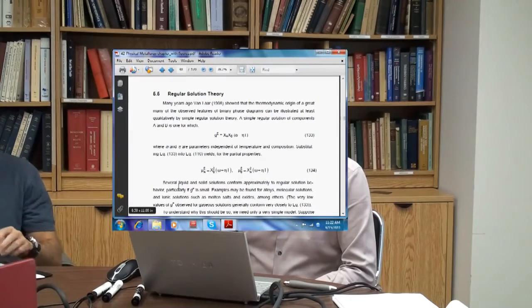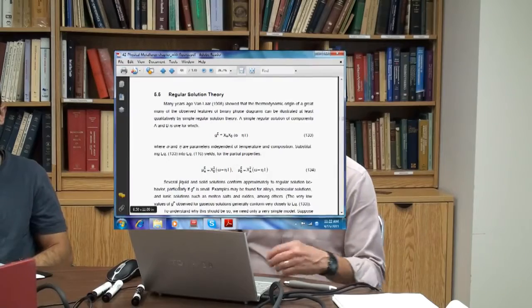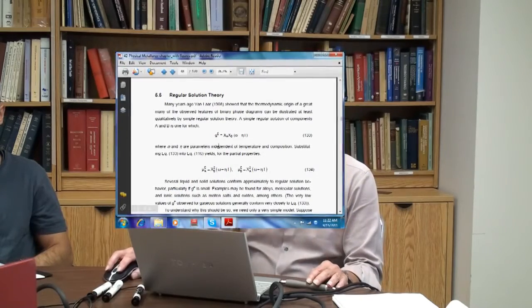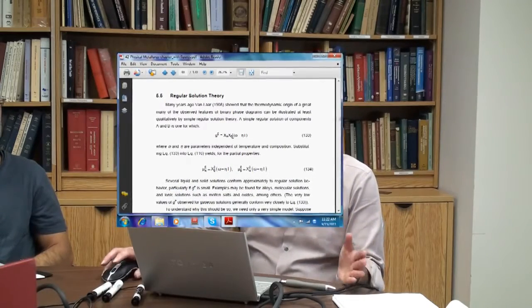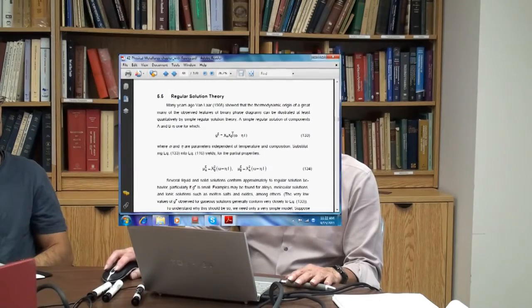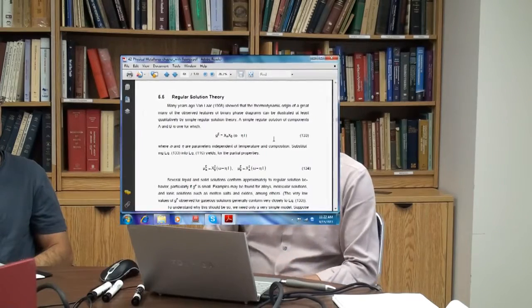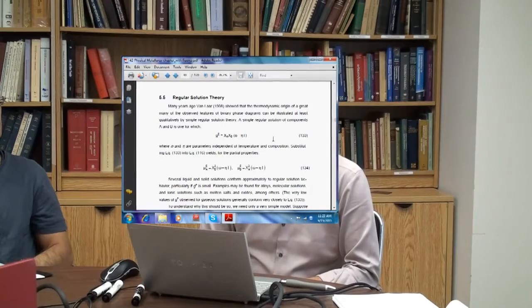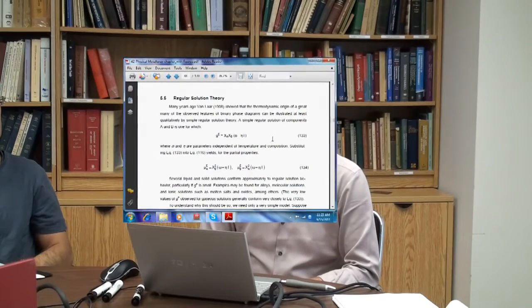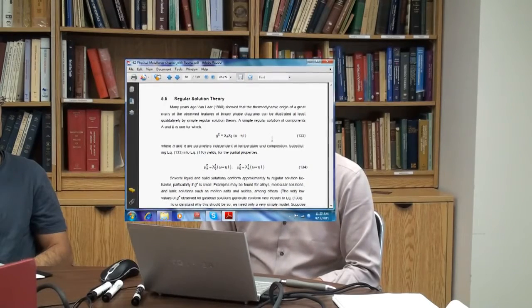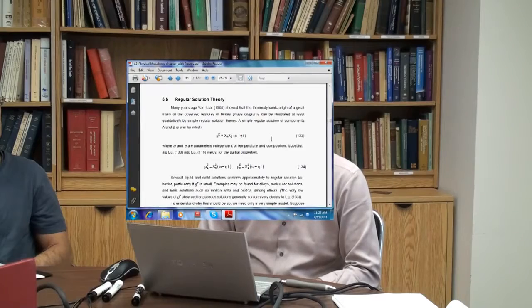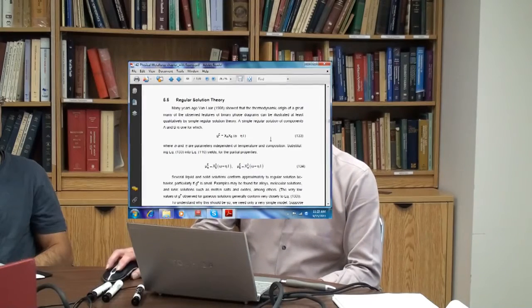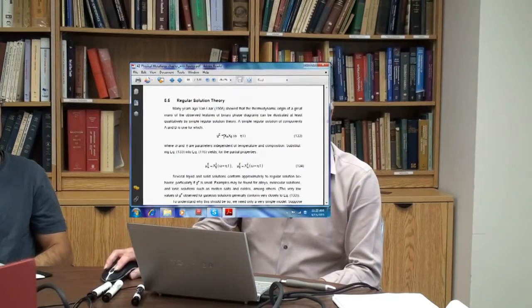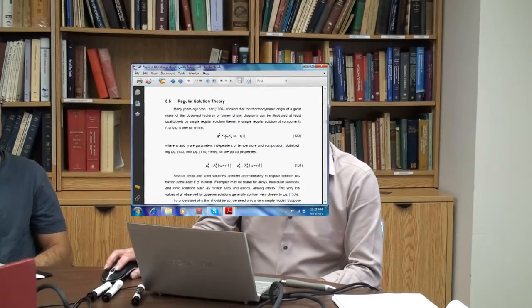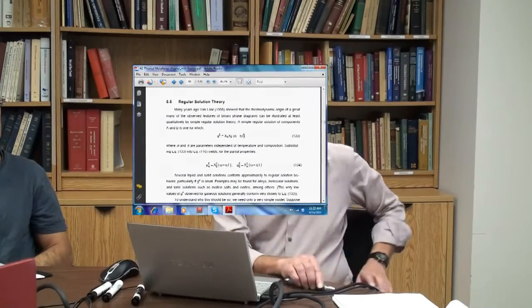Okay, a simple regular solution. This is a definition of a regular solution: the excess Gibbs energy of a binary solution is the product of the mole fractions times omega minus eta T, where omega and eta are constants, independent of temperature and independent of composition. So your integral excess Gibbs energy is then parabolic. X_A is 1 minus X_B, so that's a parabola. I drew it over here.